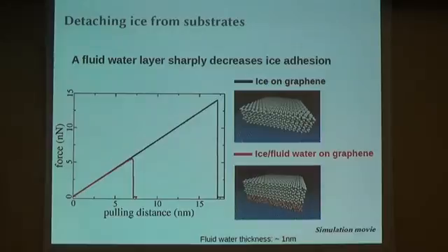So some nano cracking may happen here because of the ice moving. So this promotes the detaching event at lower forces. So the water layer somehow enhances the nano cracking initiation, if you like.